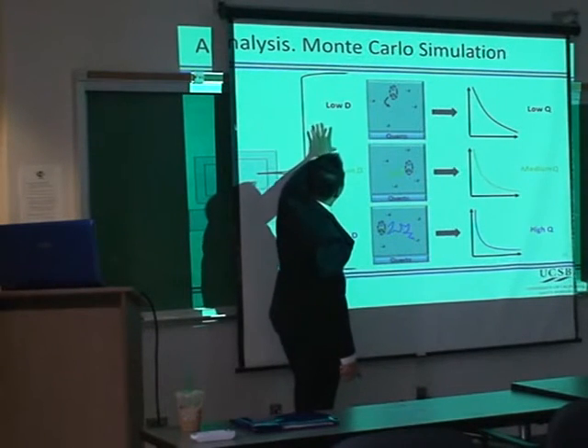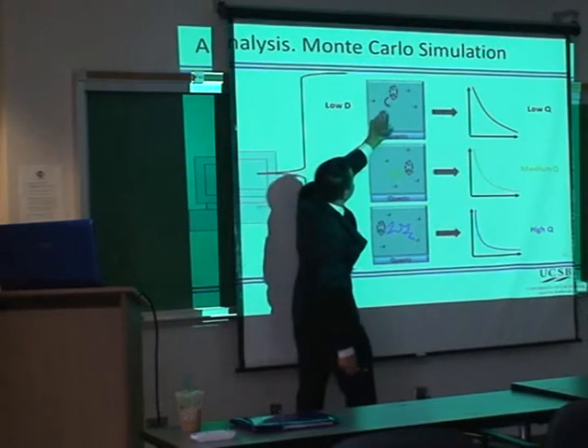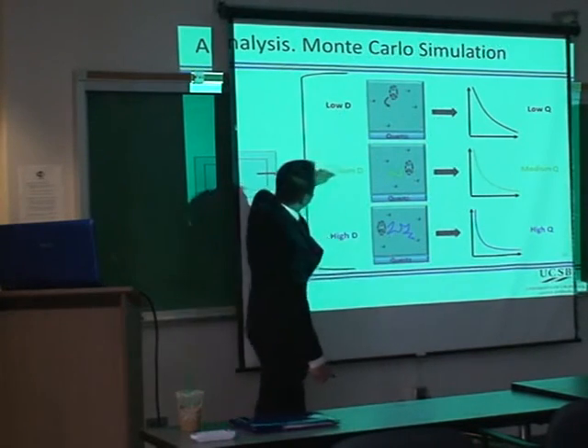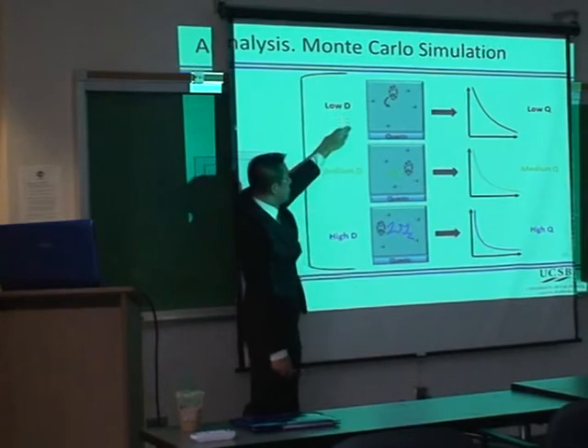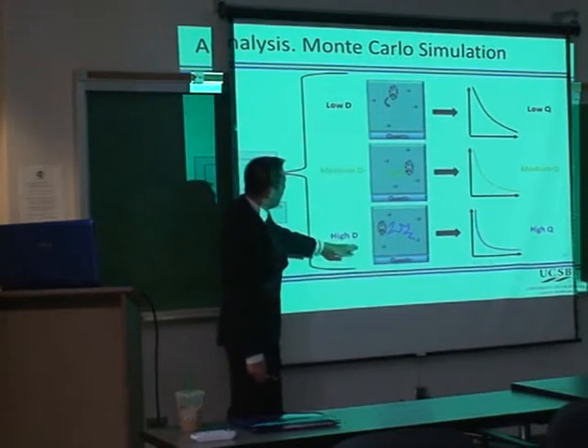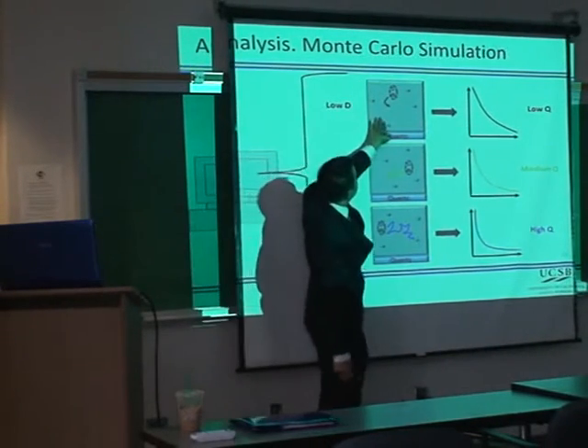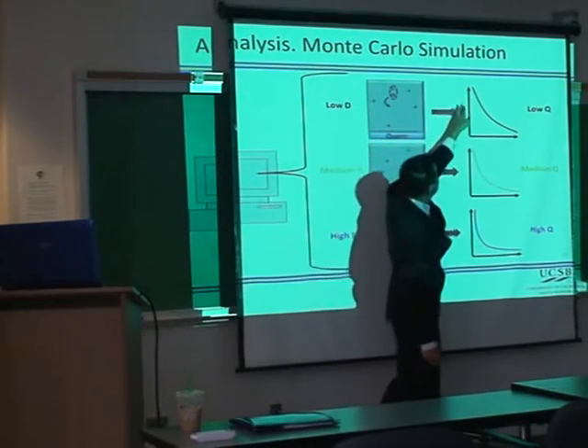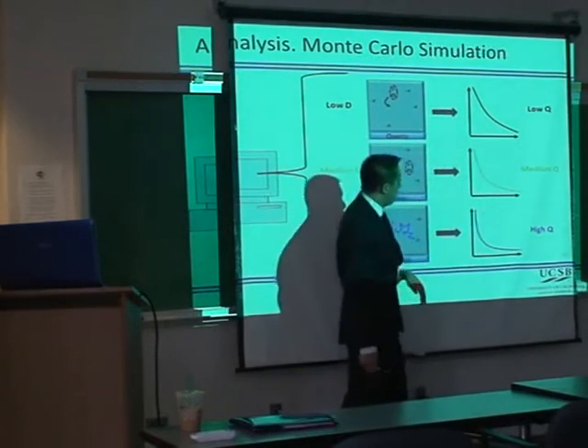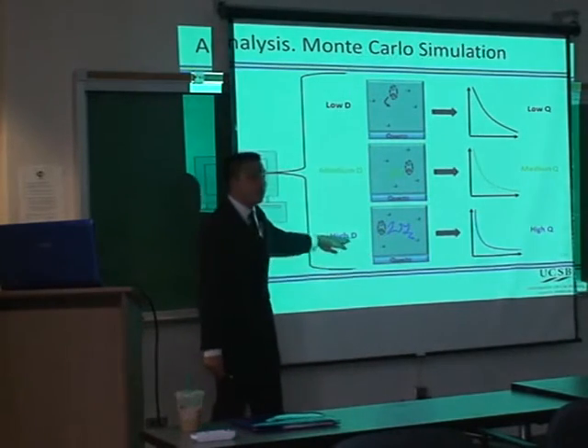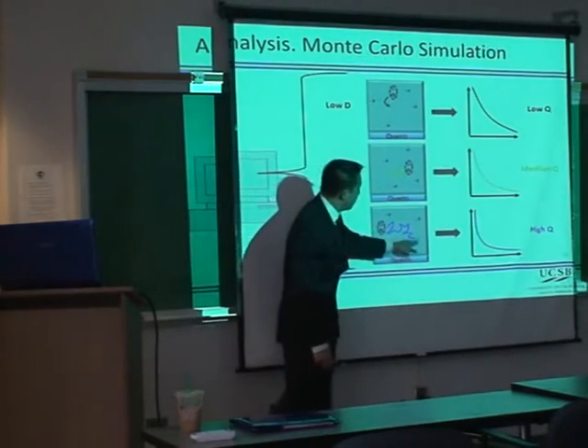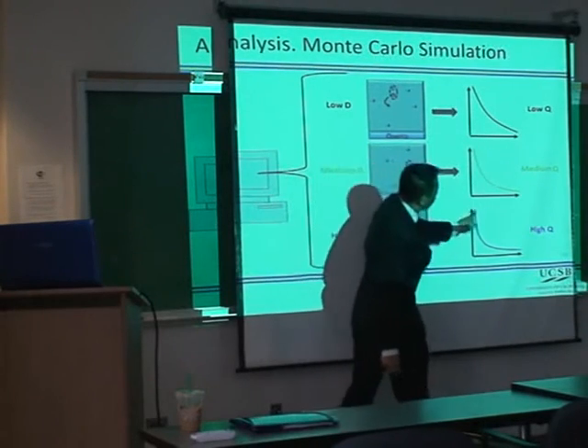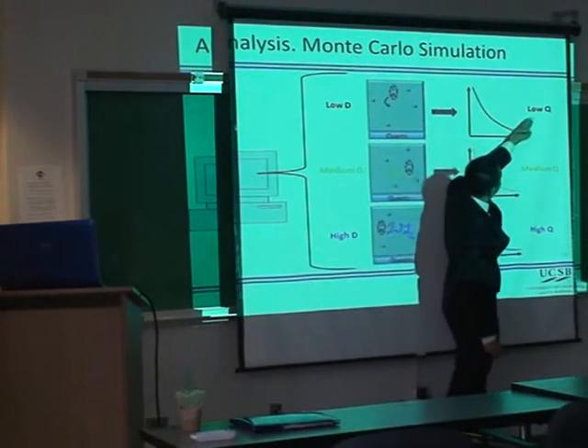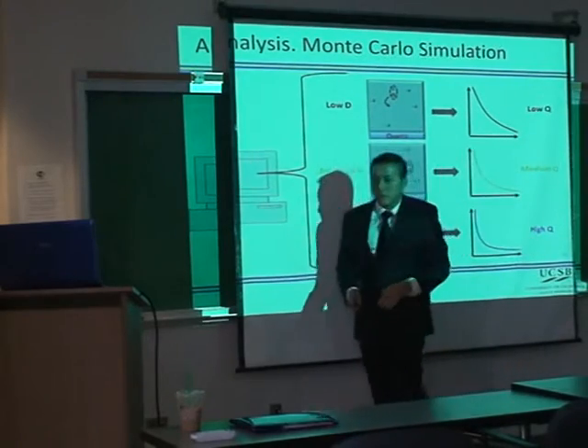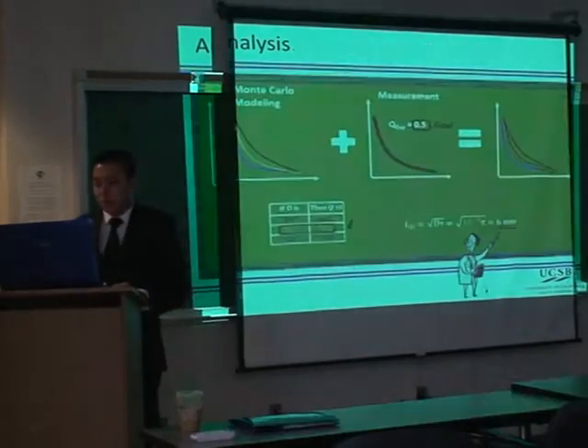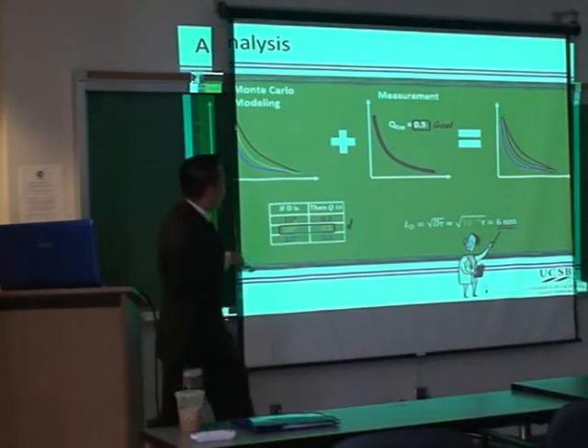And to give an example, it could basically run a simulation of exciton diffusion for a couple of different situations. Let's say for low diffusion, medium diffusion, and high diffusion. For a low diffusion, not many excitons will be quenched, so you should have this pretty broad curve. But when you have a very high diffusion coefficient, these excitons are more likely to be quenched by a PCBM, therefore the lifetime will be cut down, and you would have this trend where you have low quench efficiency to high.